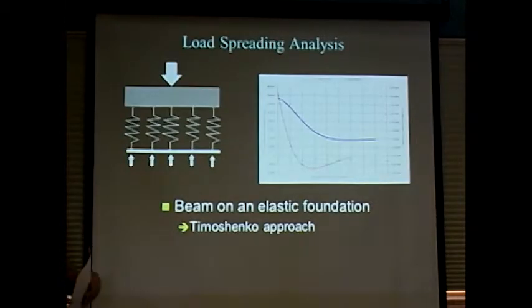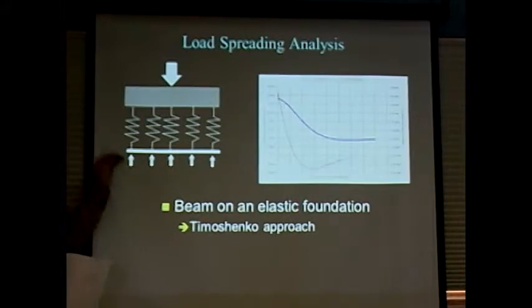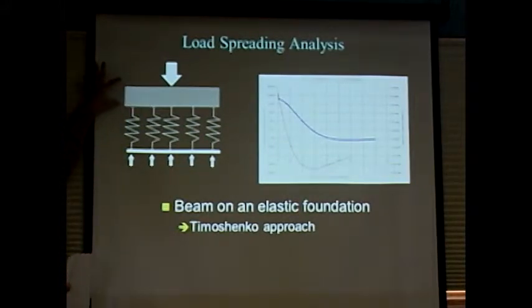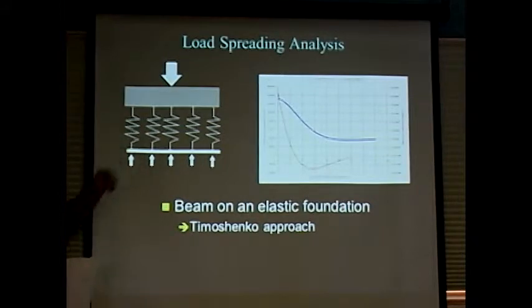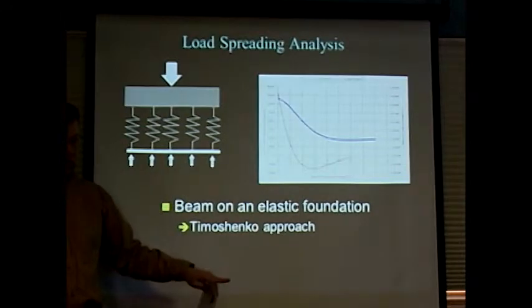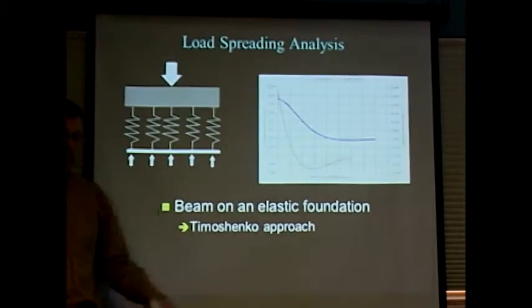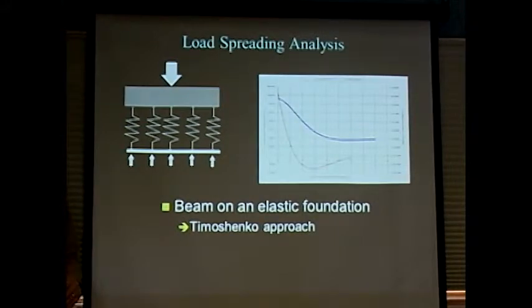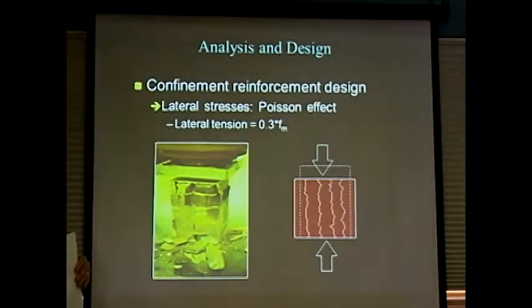And we used a classic Timoshenko approach, looking at this concrete beam resting on a somewhat flexible foundation, which is the masonry wall, and found that loads tend to spread out to a maximum effective width of about 4 times the wall thickness. That was pretty interesting because if we're designing modern masonry, I usually assume load spreads out to 6 times the wall thickness. It's kind of a rule of thumb that's written into building codes and all. And so 4 times the wall thickness made sense to me just because old masonry is not as stiff as modern masonry.